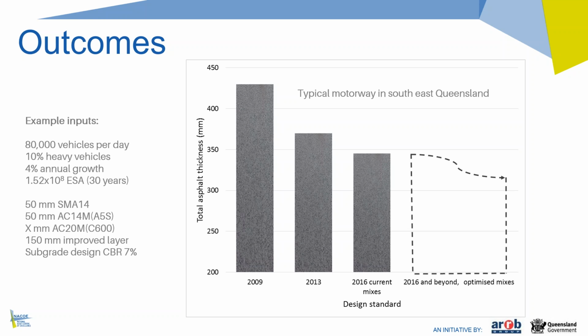to about 370 mm. This technical note introduces further improvements based on more recent research and will bring immediate benefits in justifying a further reduction in asphalt pavement thickness to about 345 mm for this example using current asphalt mixes. The chart also shows further reductions that should come from optimising asphalt mixes for fatigue performance, and that's where I'm going to hand over to Eric, who will elaborate on the mix optimisation aspects.